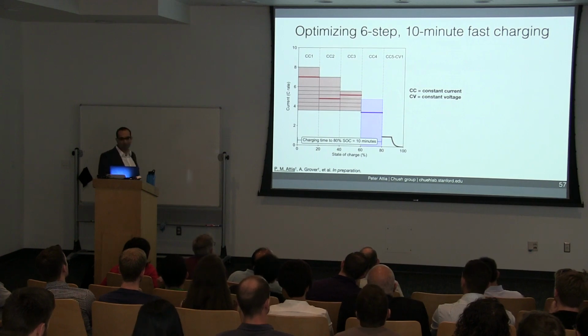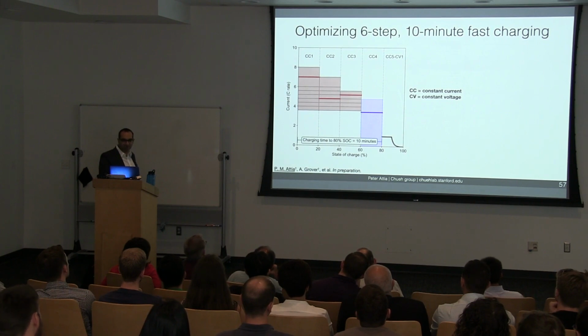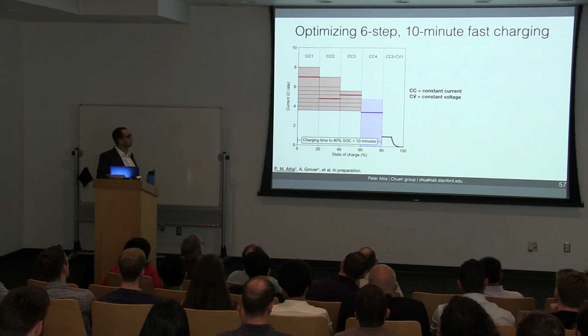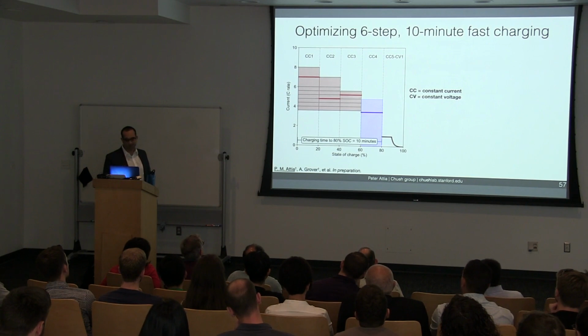So here we want to find the longest lasting combination of current steps that still charges in 10 minutes. This plot illustrates an example of our 6-step fast charging protocols. The last 2 steps are fixed for all protocols, which leaves 4 free parameters. However, we also fixed the charging time to 80% state of charge to be 10 minutes. So this additional constraint means that we have 3 free parameters, CC1, CC2, and CC3.